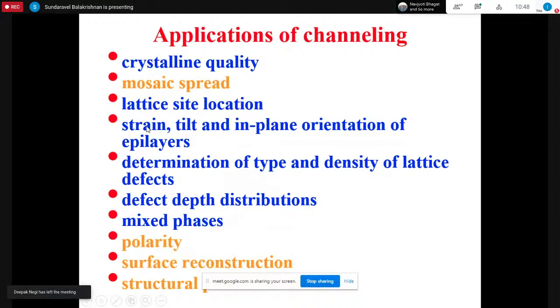And suppose you have an epitaxial layer grown on a substrate, there will be strain due to lattice mismatch. So you can determine strain in this material. Sometimes it happens that the epilayer orientation can get slightly tilted with reference to the substrate orientation. So we can find that tilt angle, and also the in-plane orientation, where to match with the lattice of the substrate, the epilayer orientation can get rotated with respect to the substrate.